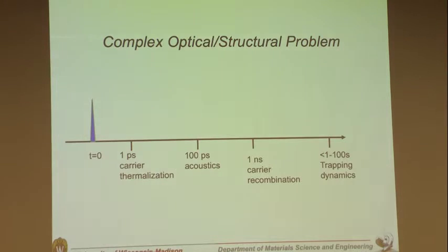And you can think of that as an acoustic effect, and that happens up to about 100 picoseconds. Then at some later time, there's an effect linked to carrier recombination. And maybe at much longer times, there's all the stuff that is associated with recovering to the ground state. And so there's things like, if your ferroelectric's not perfect and you have dangling bonds, maybe you can trap some charges and so on.